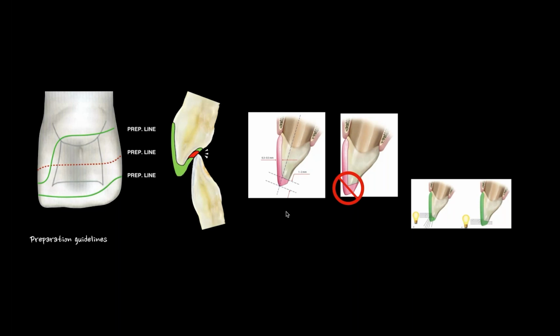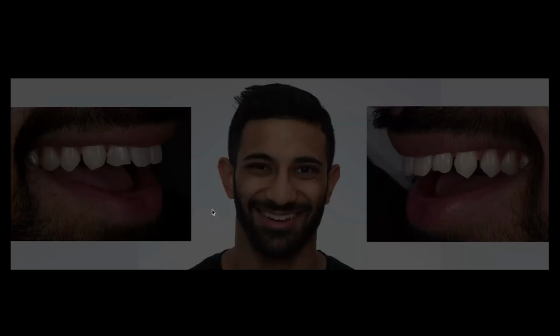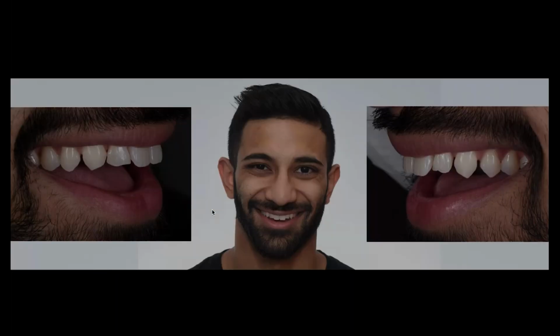and you're dictating material, because I no longer want to stay in feldspathic. I kind of have to go to lithium disilicate at that point because of the functional concern. And then my lithium disilicate becomes a wear factor for the lower incisal edge position. Feldspathic does too, but not as aggressive as the lithium disilicate. So think about those things as we're going through our preparation designs and how we communicate with our clinical partners.